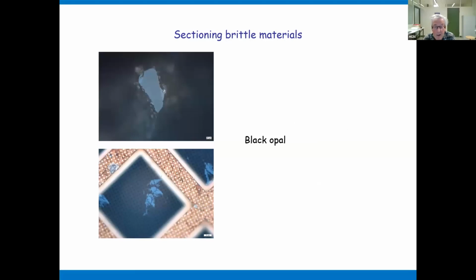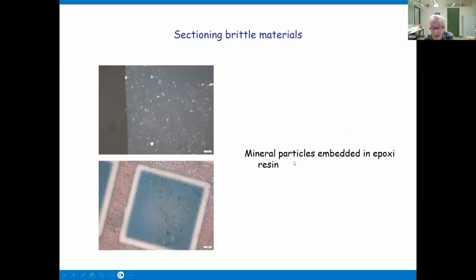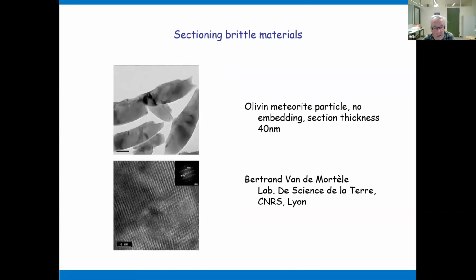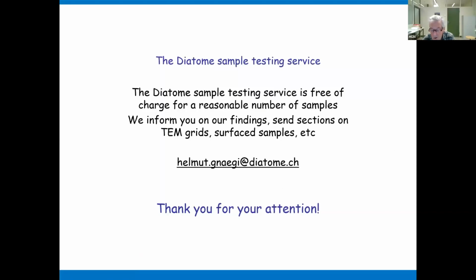Black opal, no damage. Mineral particles embedded in epoxy resin. Again, now you see a number of knife marks after the cutting. I imagine that in these mineral particles there were some quartz particles causing the damage. Natural molybdenite, olivine meteorite particle, and they had a little bit of damage using a 35-degree knife. I had no damage with the 45-degree diamond knife. So, damage on an inclusion in a soft matrix, yes. Damage on fairly brittle samples, rather no.